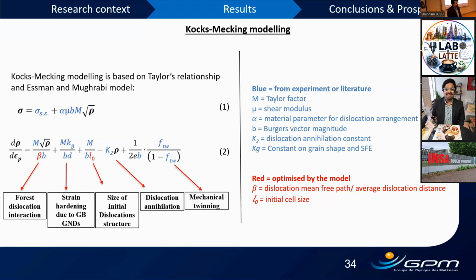The value of the dislocation density obtained from this model is compared to the result obtained in the literature. It is quite similar to what we find in the literature after deformation, the dislocation production rates, and what the final dislocation density might be, which is predicted by the model. It quite matches the value that we get from the literature.